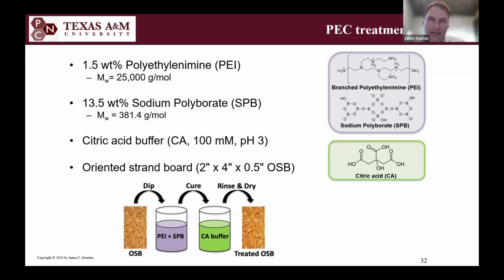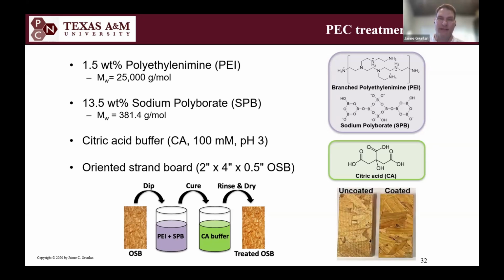So here I made a polyelectrolyte complex with branched polyethylenimine and sodium polyborate. Boron also has the right chemical mechanisms to help stop fires, similar to the way phosphates work. In this case, the SPB and the PEI, we ionically cured it with the citric acid buffer, and then we call it treated OSB. We dip the wood into one solution, into a second solution, and then it's treated. So it's a two-step, water-based treatment. And you really can't tell the difference between a coated piece and an uncoated piece of wood at that point.